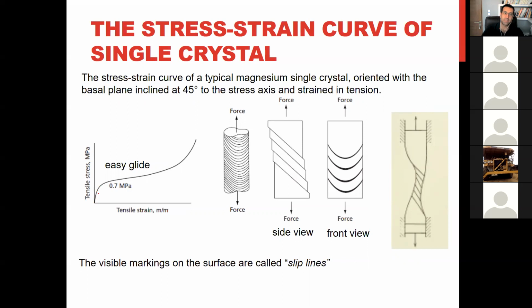But when we increase the load or tensile stress, it depends on this angle, which in this case is such that the slip plane is at 45 degrees to the direction of the tensile load. So the shear stress is minimum. So at this stress, for example, the formation of plastic deformation starts. It means one of these planes that we have inside the material, in one of them, slip can happen. Not necessarily in one, it can happen in several.